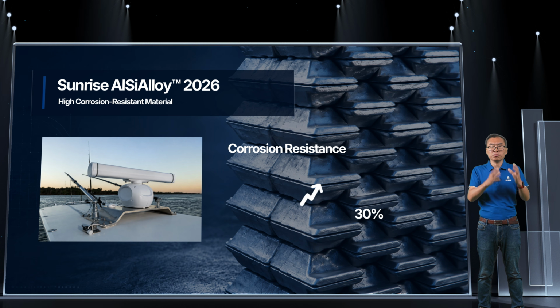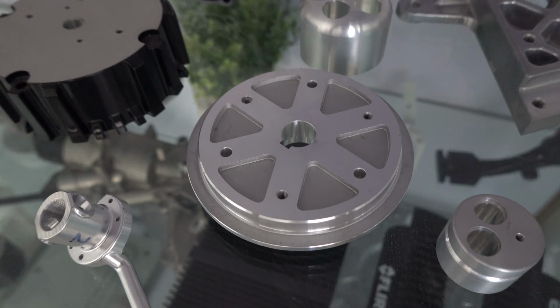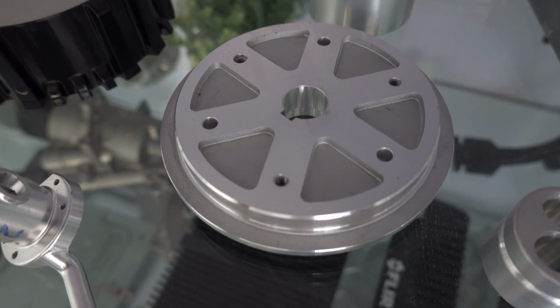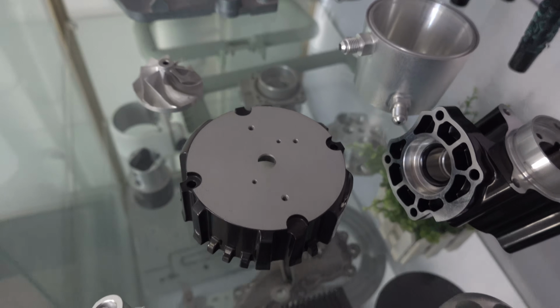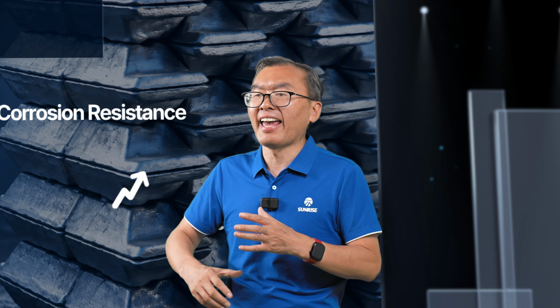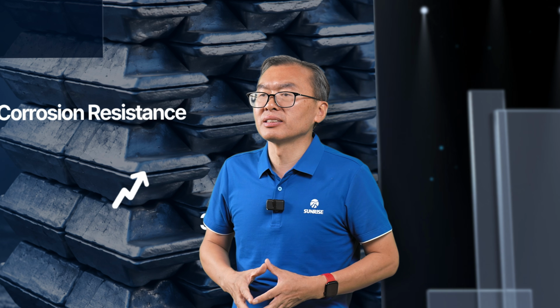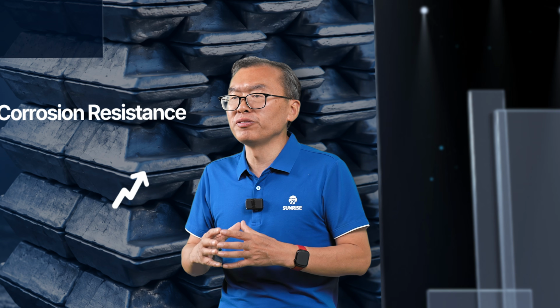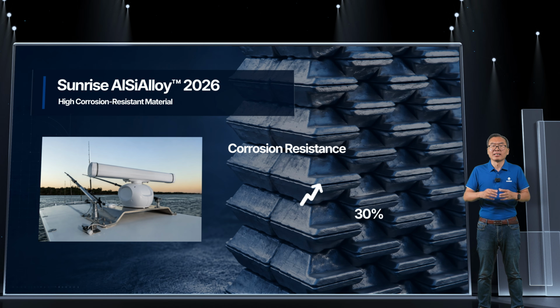Then comes Sunrise AlSiAlloy™ 2026, high corrosion resistance material. For marine parts, corrosion resistance is not only about the alloy grade. It depends on composition control, melt cleanliness, microstructure, and internal defects. With AlSiAlloy™ 2026, we focus on controlling sensitive elements, reducing inclusions and oxide films, and improving material stabilities. Our target is to improve corrosion resistance by 30% under the same validation conditions.